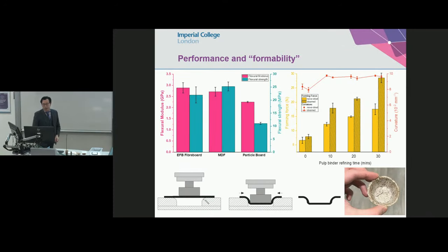So what Daru did essentially was to measure the performance of these fiber boards down here. They are comparable to your conventional MDF, whatever that you're writing on at the moment. They are made out of MDF, so it is comparable to that. In terms of bending modulus, bending strength, it is actually better than particle boards, so that's good news. So this one has at least improved performance.